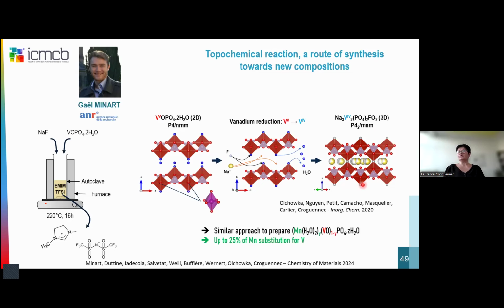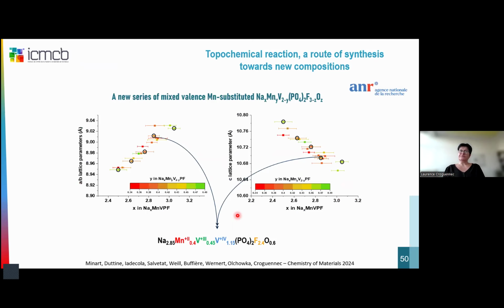So we were able to substitute manganese in these structures with exactly the same approach. It means preparing this precursor here, and we were able to substitute up to 25% of manganese for vanadium in these structures. So in fact, we were also able to develop a new series of materials with a variation of composition in manganese and vanadium, but also in fluorine and oxygen, and also in sodium, as you can see here with the lattice parameters versus the composition in sodium in this material. You can see here a series of materials.